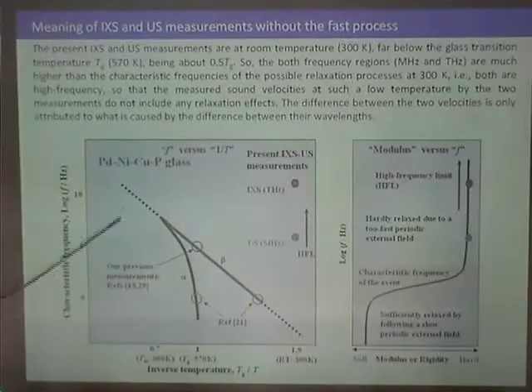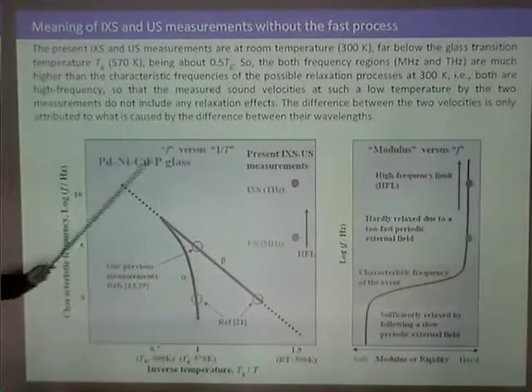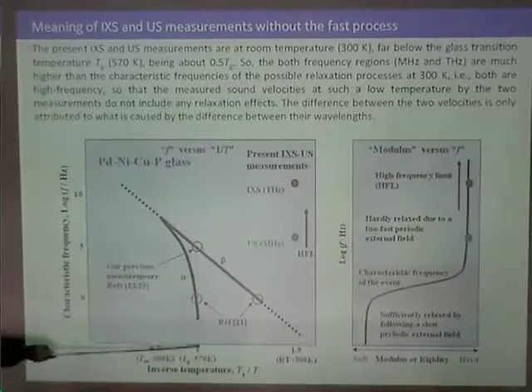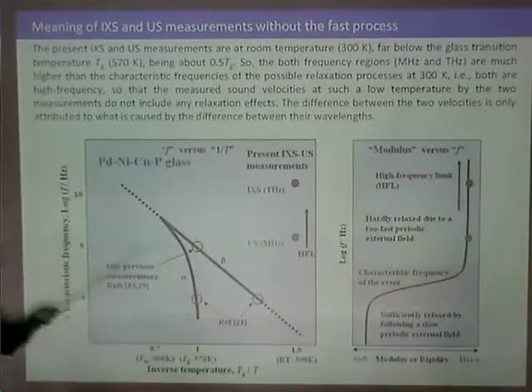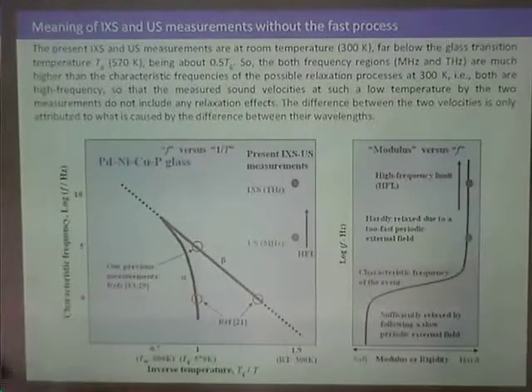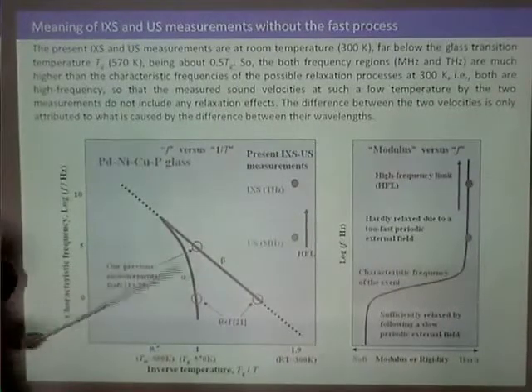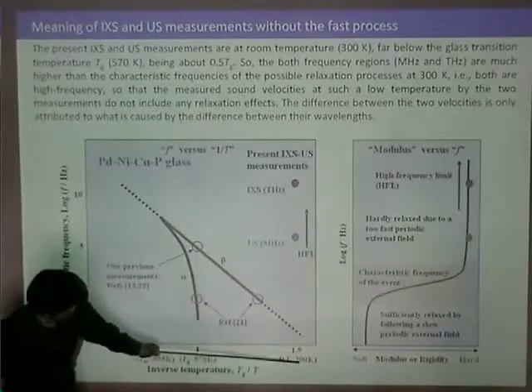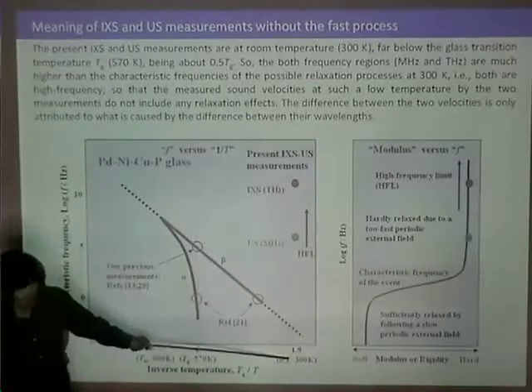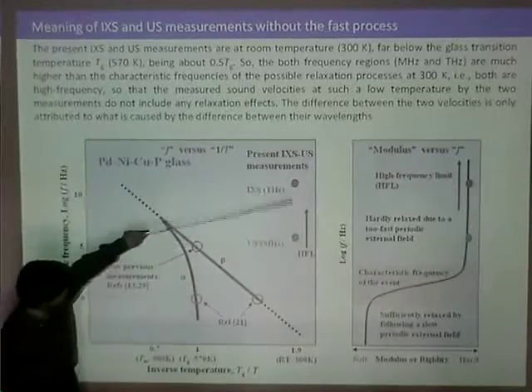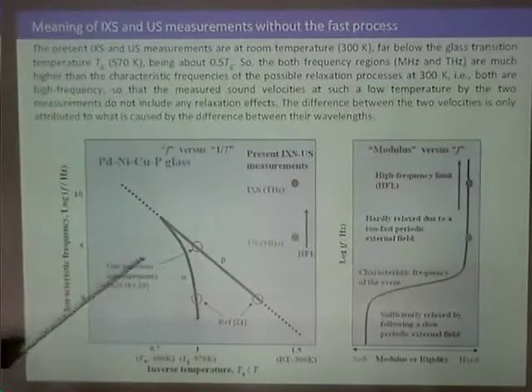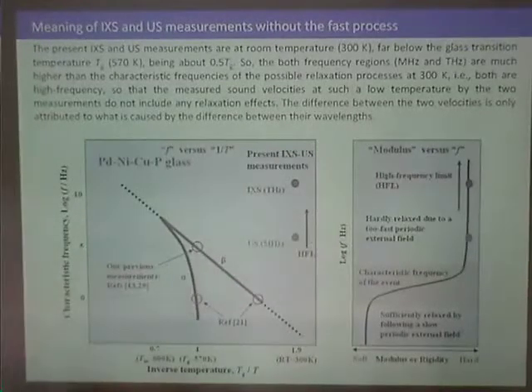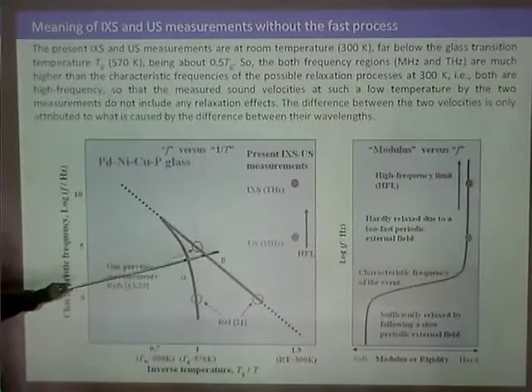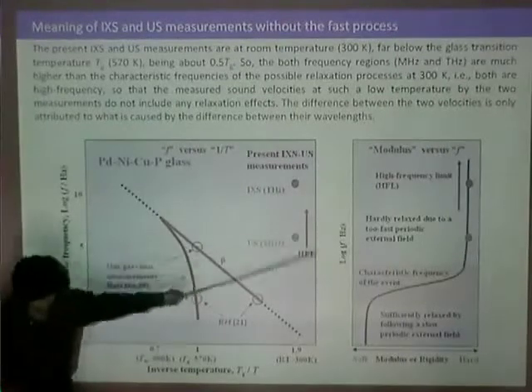So this is a typical characteristic frequency map of the palladium nickel copper phosphorus metal glasses. TG is located here, this is the beta relaxation curve, Arrhenius behavior, and this is the VFT curve, the alpha relaxation. Our measurement temperature is at this point, with frequencies megahertz and terahertz. So both frequencies are high compared to alpha and beta relaxation.